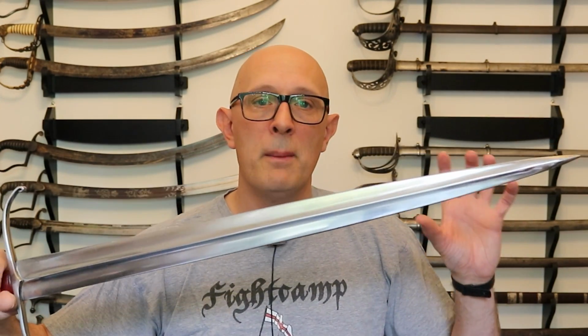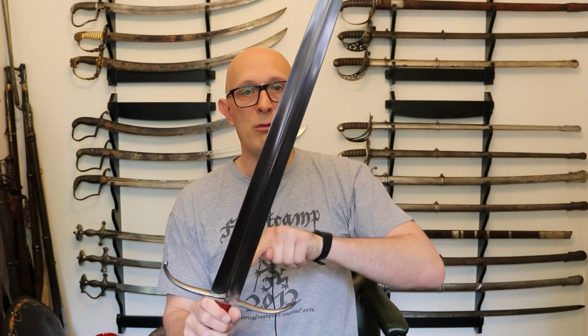Now it's worth mentioning pattern welding again, because this comes back into this kind of comparison, I suppose. And in the medieval sword world, certainly by the date of this sword, 15th century, they were just making swords out of one piece of processed steel essentially. But if we go back to the Viking era, pattern welded blades were popular, and if we go all the way back in fact to the Roman era, pattern welded blades were an option for making a blade. Again, it's about spreading out the rubbish that you don't want in the blade, things like the slag and other stuff. But also what you can do is weld a hard edge around a softer